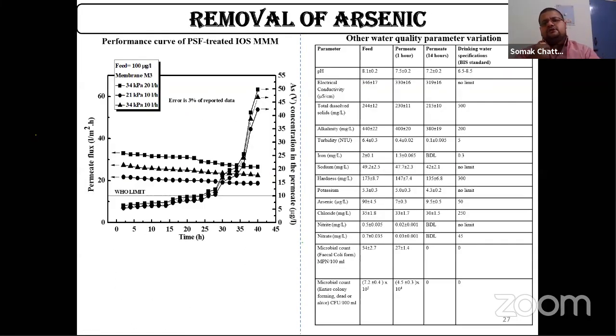We also achieved a successful result when we used polysulfone and treated iron ore slime mixed matrix membrane, and we were able to see that for a time of roughly around 26 to 28 hours, the breakthrough time was achieved for this kind of membrane.